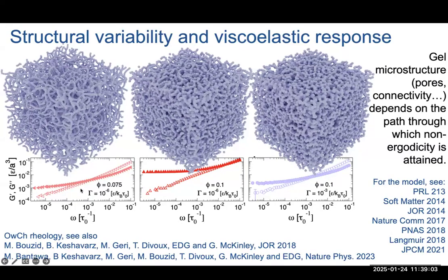But if I look at the rheology of this, these are the results of oscillatory viscoelastic tests in simulation that we've done precisely with the chirps technique that I was mentioning before. And so you get the spectrum over a broad range of frequency, these spectra, the G prime and G double prime, the storage modulus and the loss modulus. They change over a broad range of frequency, which is what you see in real materials.